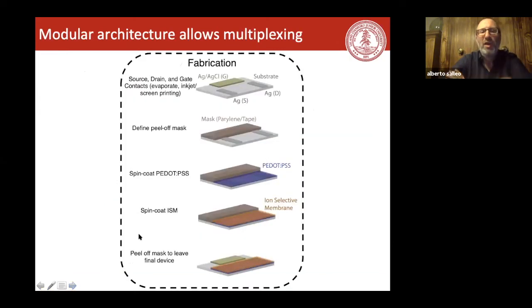So, like I said, one nice thing is that you can integrate this pretty easily. And because these are polymers that can be patterned and deposited very easily, you can make sensors very cheaply. So what you can do is deposit silver by inkjet printing, for example. This can be done routinely nowadays. And then you can chlorinate, you can make the silver react and it turns into silver chloride. So you can make your silver chloride electrode the same way. Then you can mask the silver chloride electrode.